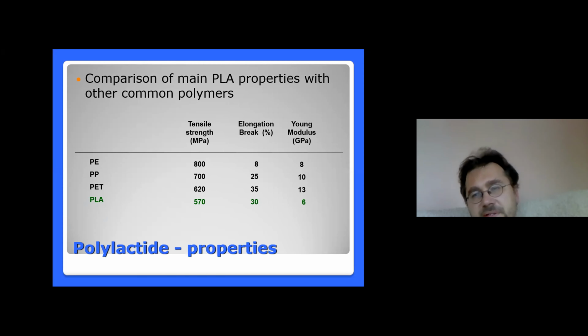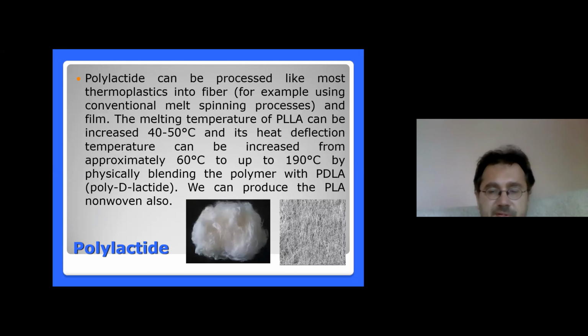So it means that this polylactide, which we can produce, has properties really close to typical polyolefins or other synthetic polymers. A big advantage of polylactide is that we can produce polylactic fibers by using exactly the same technical equipment which is used for polyolefins and for typical thermoplastic polymers. So exactly the same machines.